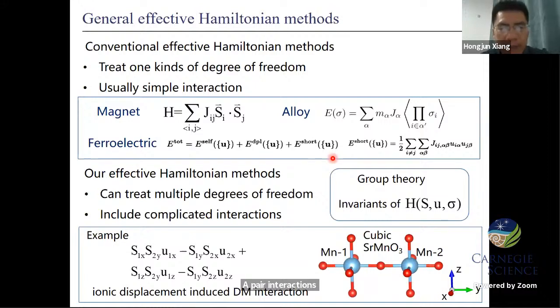In our package, we try to generalize this effective Hamiltonian method. So we are trying to treat multiple degrees of freedom. For example, the system might have a spin degree of freedom and an atomic displacement degree of freedom, and may also have an alloy degree of freedom. The interaction between these degrees of freedom could be complicated, so we are trying to encode all kinds of complicated interactions. We use group theory to find out what kind of interaction will be present in a system with multiple degrees of freedom. So we find the invariants of these different terms.